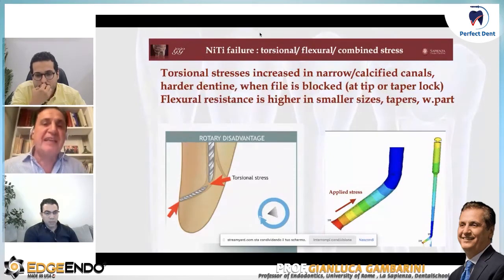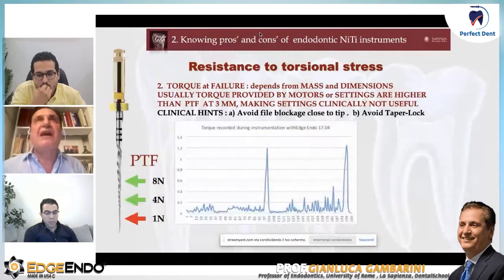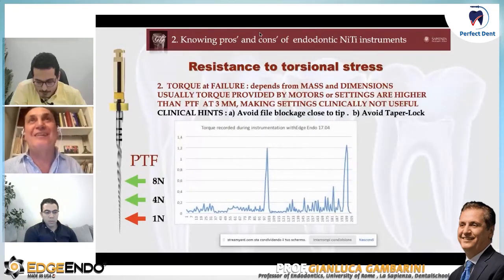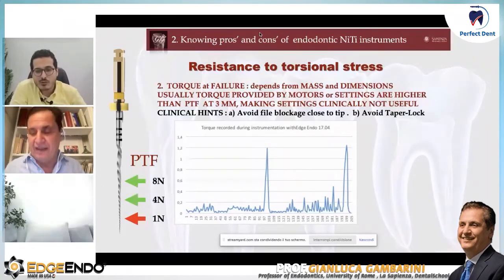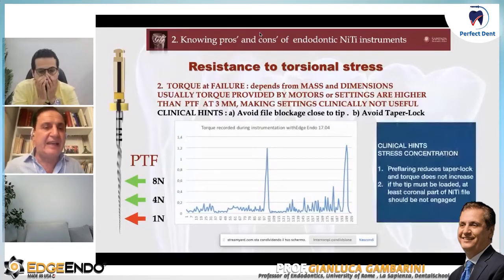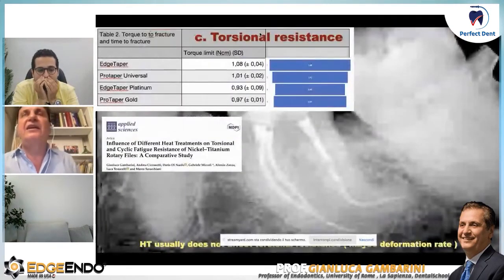stress. So speaking about the torsional stress, we can also measure resistance to torsion by making the traditional ISO test. And obviously the torsional resistance changes, and this is also quite interesting, but we could talk even one day about whether the stresses are really present in the instrument, because in all our studies, we measure the torsional resistance only at 3 millimeters. But the torsional resistance varies all along the file's working length. And interesting here is that if we measure the effect of the heat treatment on the torsional resistance, we may say that it doesn't really change too much. It doesn't really improve, or decrease, the torsional resistance of the file. So this is quite an interesting thing.